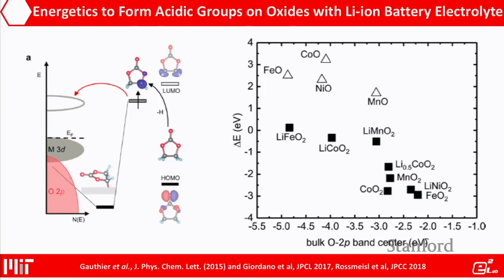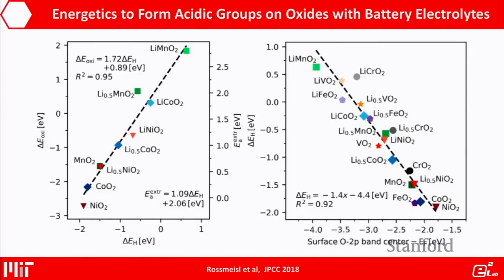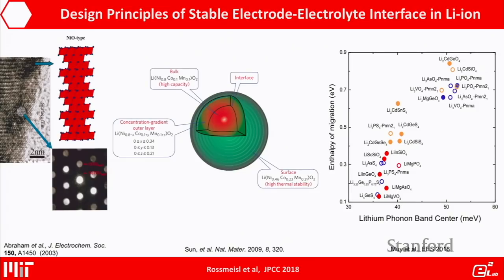And this is one of the reasons that if you develop these high energy nickel containing positive electrodes, you can actually have a poor cycle life because of generation, we believe, of these protic species that react with the salt and generate essentially surface films with very high impedance that influence cycle life. You can do more, and essentially we have computed over 100 of these compounds. Essentially this correlation that we developed holds. You can actually simplify the reactions just by looking at hydrogen binding onto different metal surfaces. And this type of thinking essentially allows us to develop stable surfaces on positive electrode materials.